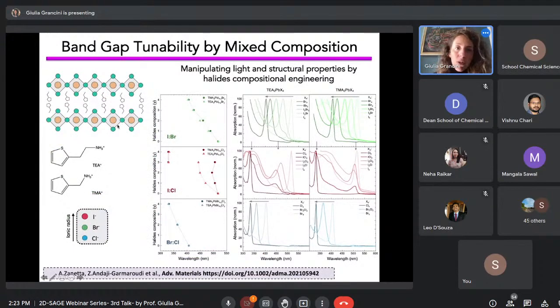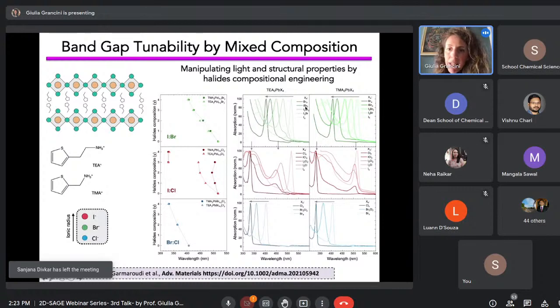So in this case, we have a pure 2D perovskite, so not 3D anymore, and we wanted to manipulate the structure by halide compositional engineering. So basically what we used are these thiophene-based cations, and then here on the green spot, we change from iodine, bromide, and chloride. And we basically engineered the halide composition. This example is very interesting because what we observe is that when you make a combination of bromide and iodine or chlorine and bromide, you do see a smooth transition of the band gap. You see that there is a red-blue shift, a linear shift consistent with the incorporation of bromide and iodide in the crystal structure.